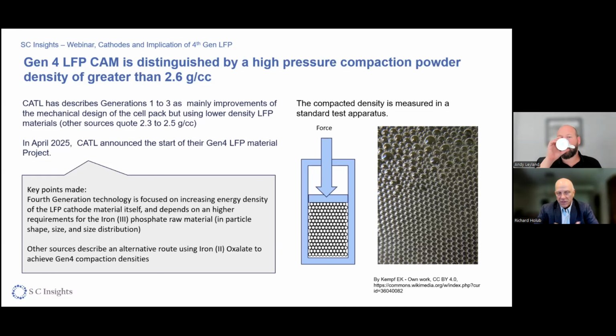But there's also a lot of improvement, as I'm sure the folks on the line are very familiar with, in terms of the cell pack design and other things. So what did CATL mention as the key thing for their Gen 4 raw material? It was mainly around the iron phosphate raw material. They mentioned particle size, size distribution and shape as being critical to their technology to make the Gen 4 material. Their technology, as I go forward, we'll discuss as the iron phosphate route. It's a solid phase synthesis route. The other route that's being published and discussed is another solid phase route, the iron oxalate route, which is also achieving the Gen 4 compaction densities.